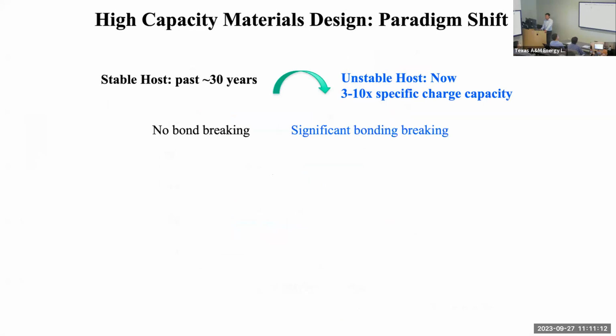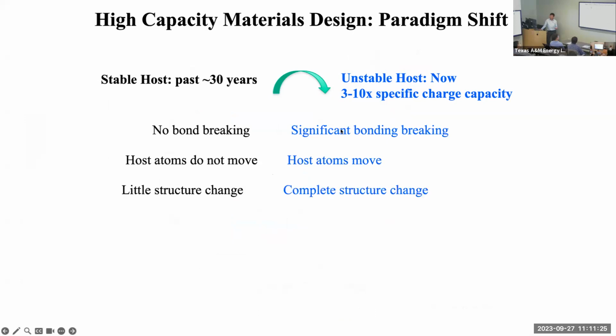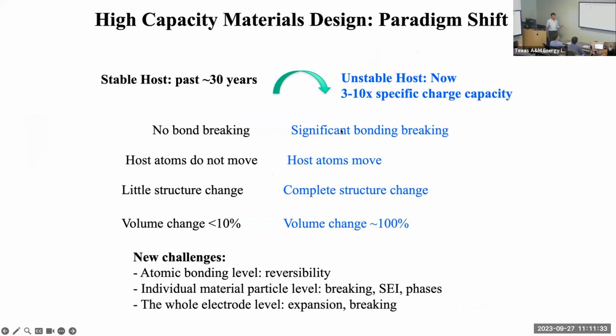Not only that, if you look deeper, the new materials on the right are not stable. When you put lithium in and out, you break the chemical bonding of the host materials. You move the host atoms a very long distance. You cause a complete structure change because of the gigantic volume expansion. And we really need to redesign the batteries in a very, very different way, from the materials and chemistry level all the way to the whole system level. That has been the topic my lab has been trying to tackle in the past close to 20 years.